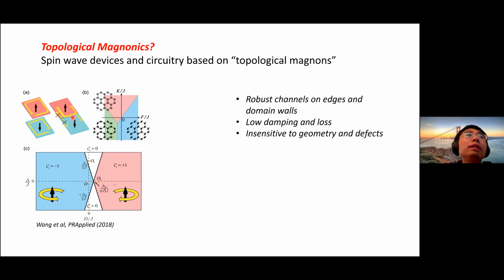Naturally, instead of having a physical boundary, if you have a domain wall between a spin up region and a spin down region, there is also going to be an edge state on this domain wall. So in this case, we have robust channels both on the edge and on the domain walls.